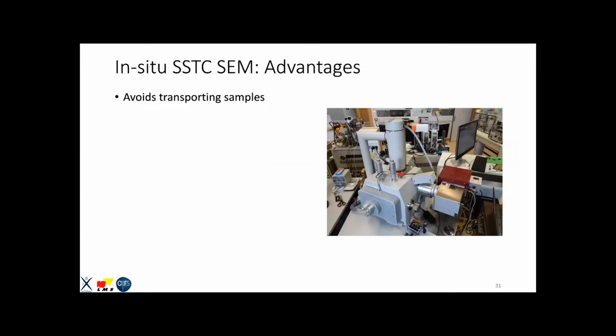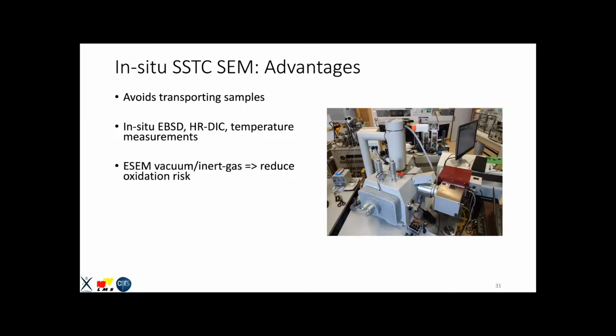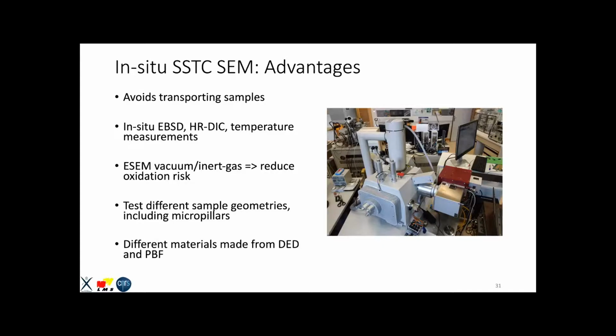Okay, so what are the advantages of this? Well, if you want to do SSTC and microscopy, the current state of the art at that time was you do your EBSD characterization, you take your sample to the AM machine, you scan it with the laser, you come back and you remeasure. Instead of that, you avoid transporting samples, you do it in situ, and you don't oxidize it because you are keeping it in vacuum. You can do in situ EBSD, high resolution DIC, and temperature measurements with the equipment we have. As I mentioned, you reduce oxidation risk by doing it under vacuum and inert gas because it's an environmental SEM. And we can test different sample geometries, including micropillars. And we can test different materials made from DED and PBF.